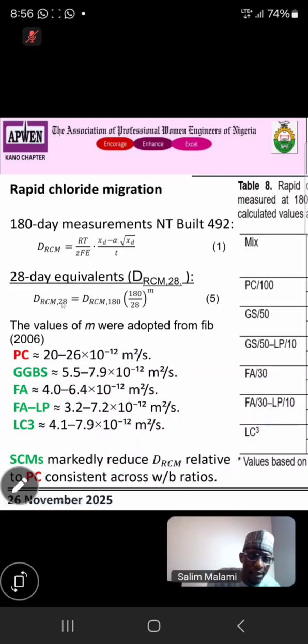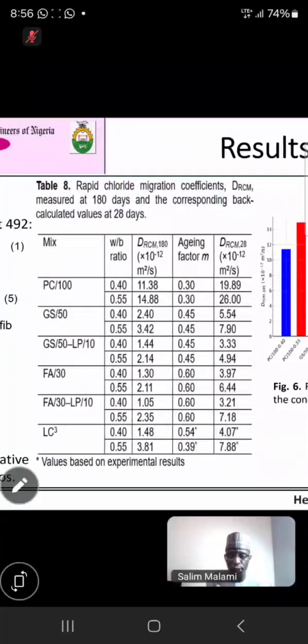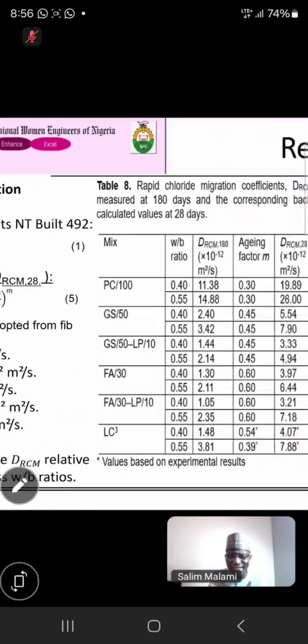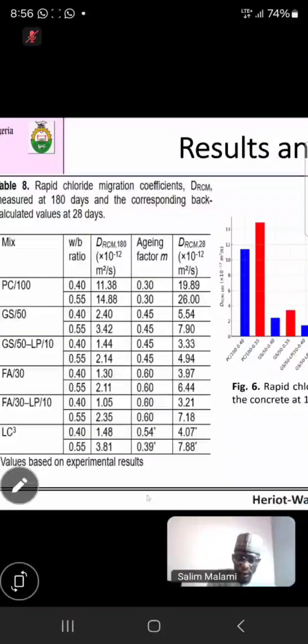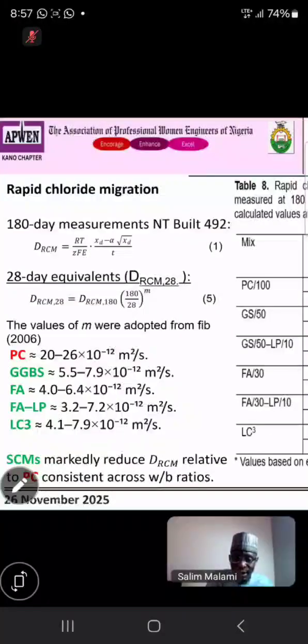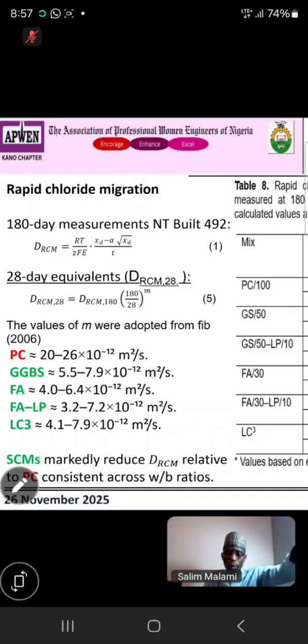So rapid chloride migration at 28 days is the reference diffusion coefficient times 180 divided by 28. Then you use the age factor. For this age factor, we use the one given by the FIB model code, because we found some different behavior in the concrete. But for LC3, there is no age factor in the FIB model code. So that's why I tested my own age factor, because we don't have it in the code. So that's why you see a star saying that it is based on experimental results.